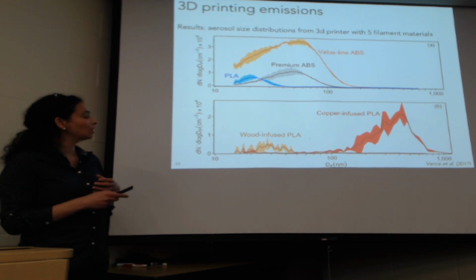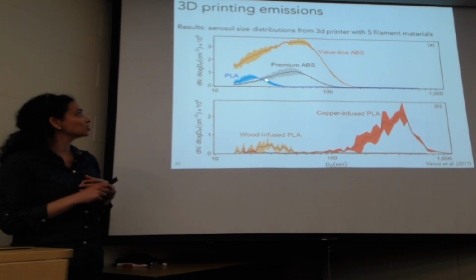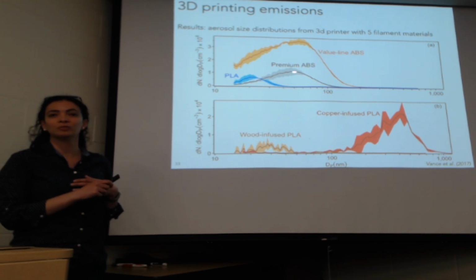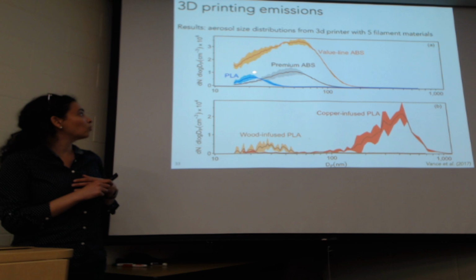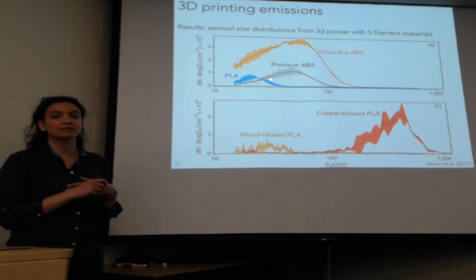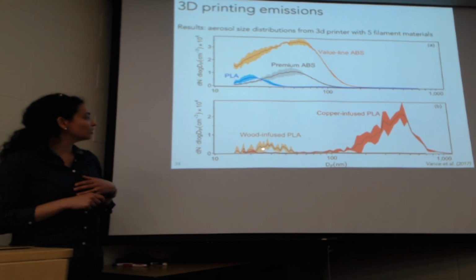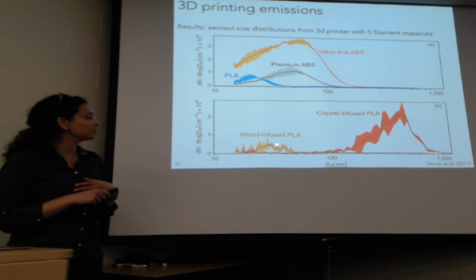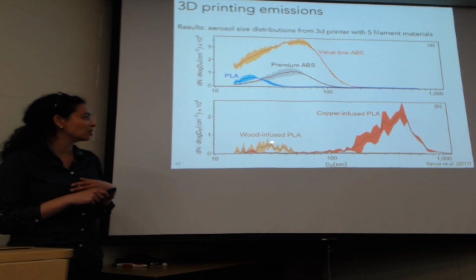Does that make sense? For PLA, emissions were, in terms of numbers, pretty similar to ABS, remember from the previous chart. But these particles were way smaller, about 20 nanometers in size. For the wood-infused particles, we also had this mode of particles, 20, 30 nanometers in size, pretty small, and there were so few of them it was hard to really tell.